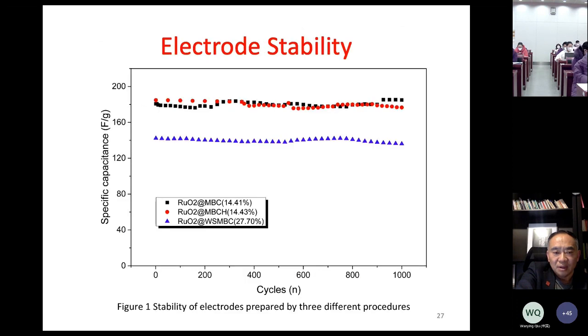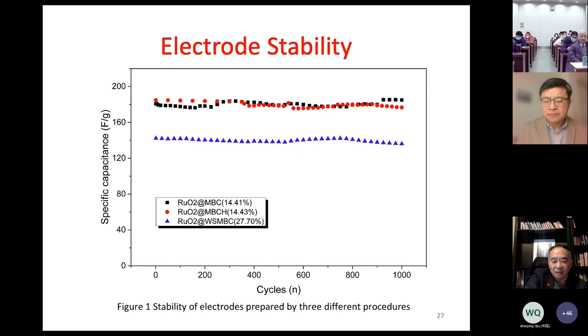So this is the electrochemical stability, and what you can see here is that after 1,000 cycles it is still quite stable. In fact, we put together another cell and ran it at 10,000 cycles, and the performance is still as good as a new cell. This is not a surprise because a supercapacitor is very much a physical device. It's not like batteries, whose performance is going to decline after a few thousand cycles.